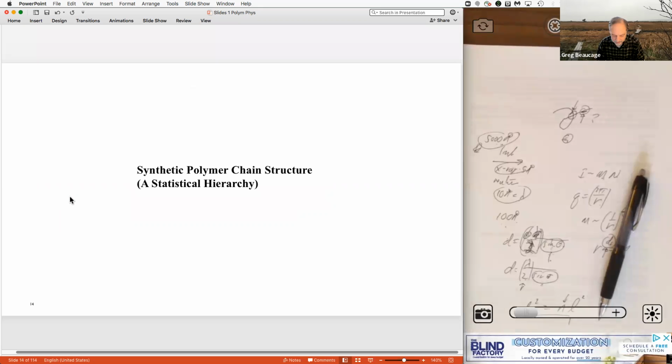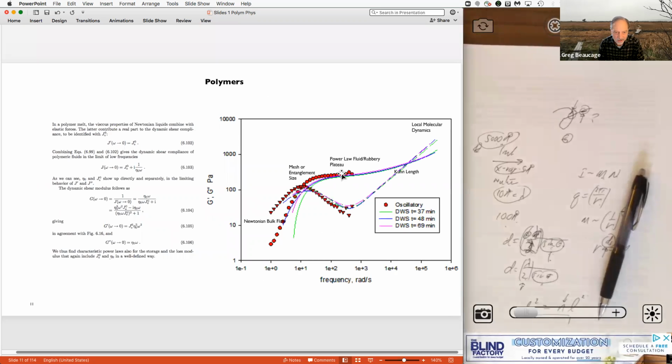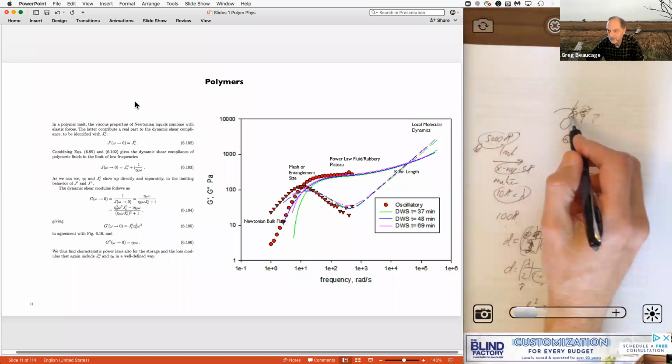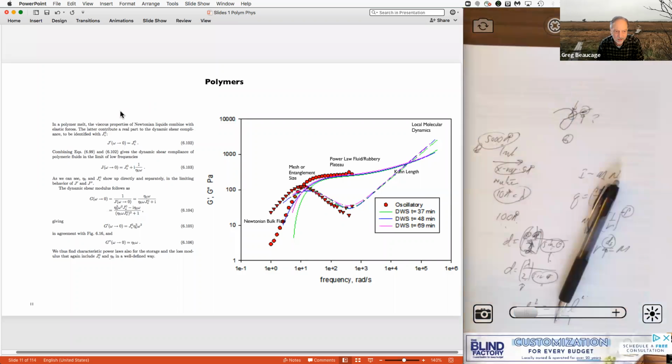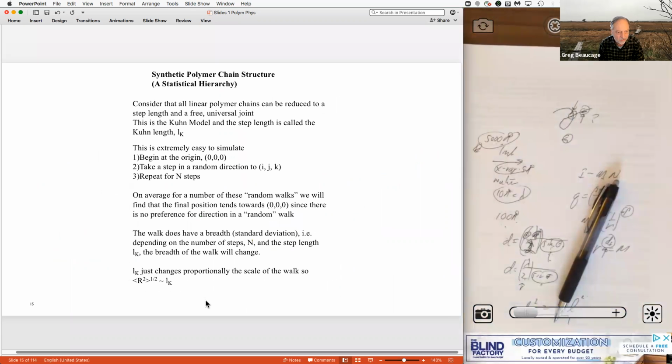You can see that for this particular polymer, a polyhydroxybutyrate biodegradable polymer, you can get power 2 here, and the analysis that you get this plateau is also reliant on a power 2. So there are cases where it matches up exactly, and it doesn't matter that it crosses over. Sometimes that works, sometimes it doesn't, and it depends what the condition is. Those are all in a melt state, polymer melt.